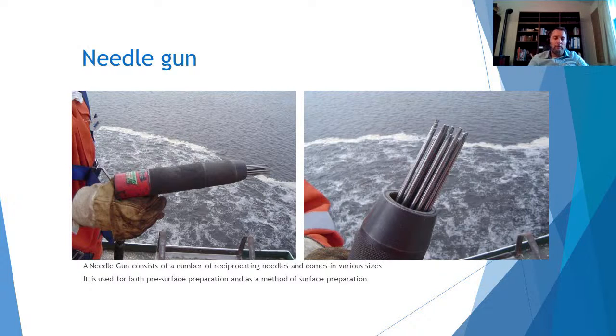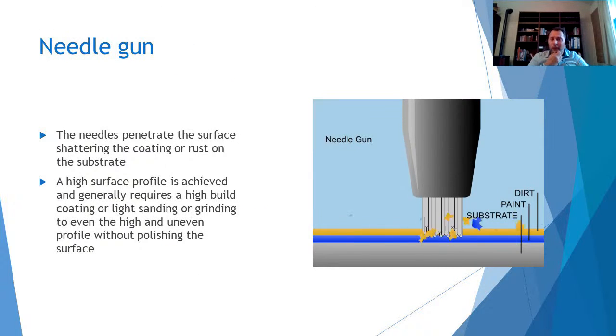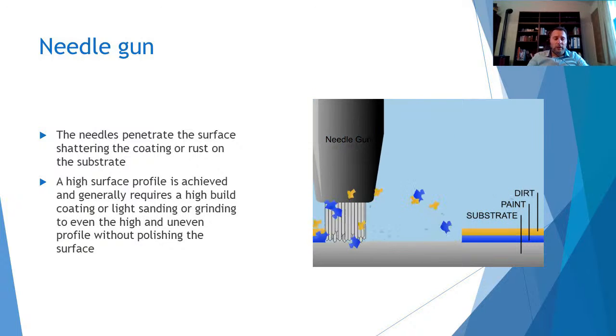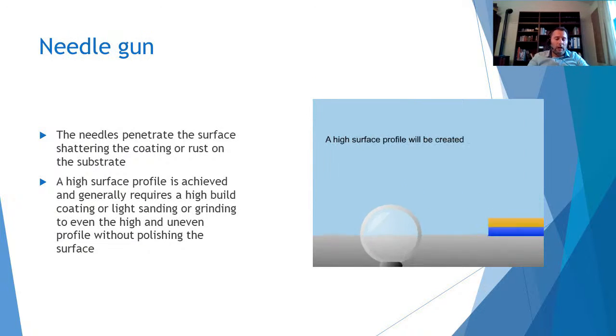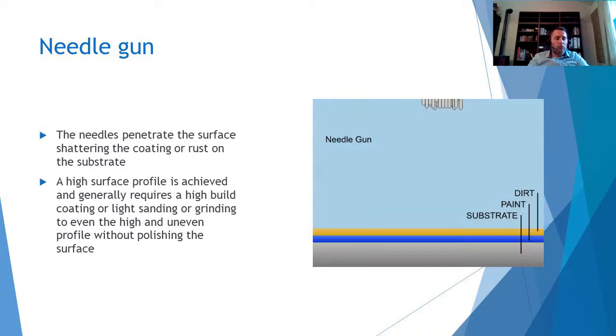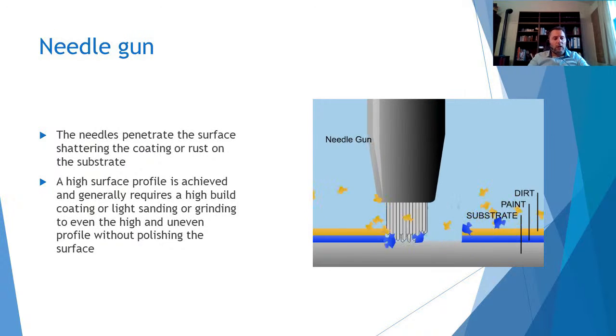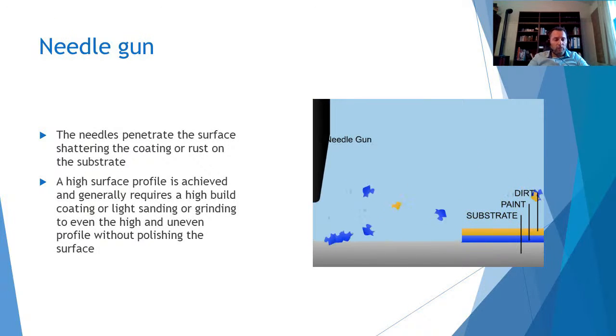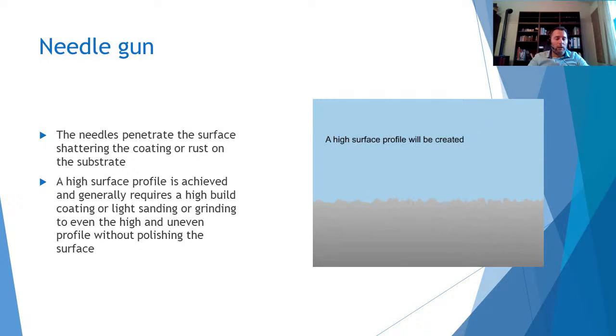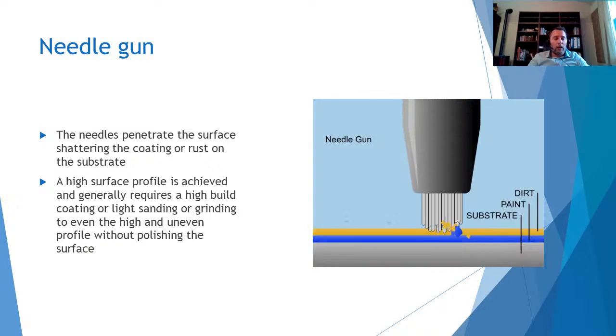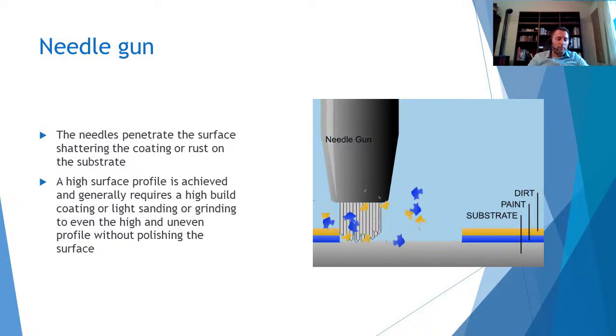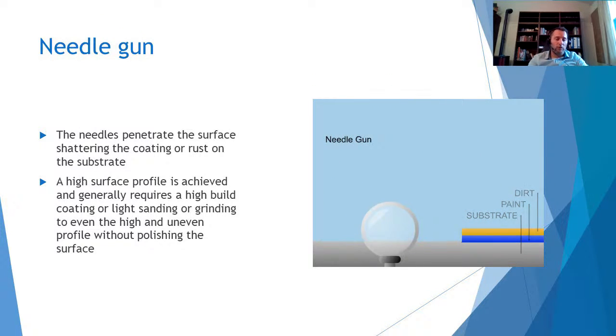Here we have an example, a video that shows us the needle gun working. The needle penetrates the surface, shattering the coating or rust on the substrate. A high surface profile is achieved and generally requires a high build coating or light sanding or grinding to even the high uneven profile without polishing the surface.